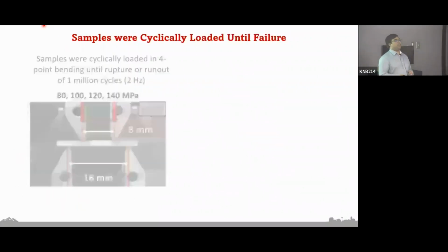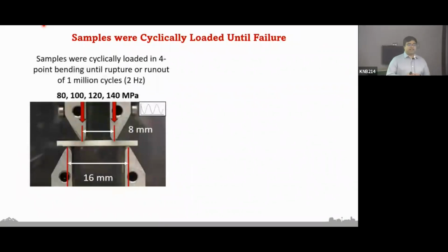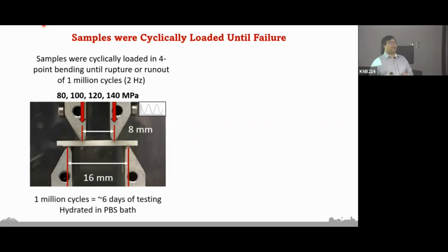So let's talk a little bit about those tests. I kind of showed you the picture of it before. We did a simple 4-point loading configuration, and we tested them until either rupture or a predefined runout of 1 million cycles. All of those samples were evenly divided based on the harvest site, the animal, and the group that they're from across 4 different load levels: 80, 100, 120, and 140 megapascals of peak load at the cyclic peak. Before I move on, I want to draw your attention to something. If a sample survives 1 million cycles, that's about 6 days of testing. So with 240 samples, if they all ran out, that would have been something like 4.5 or 5 years of nonstop running our machine. Thankfully, they didn't do that, and I only had to run the machine nonstop for about 2.5 years.